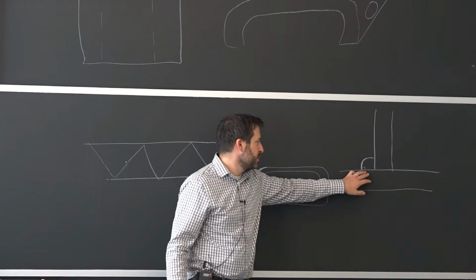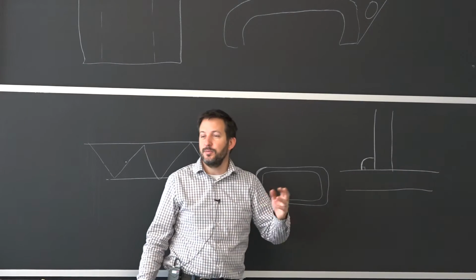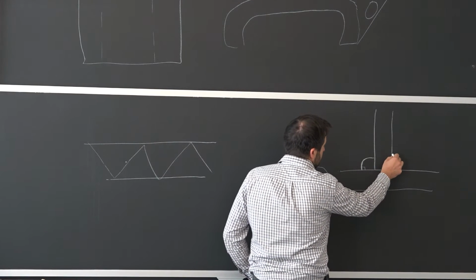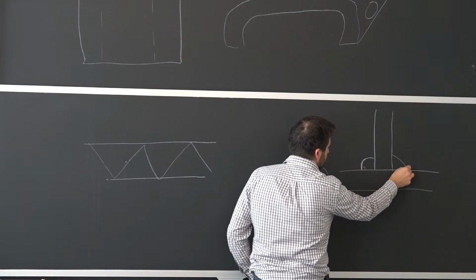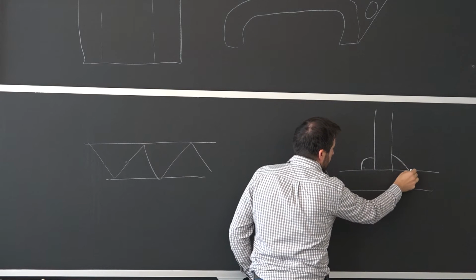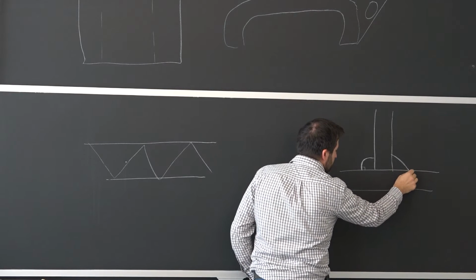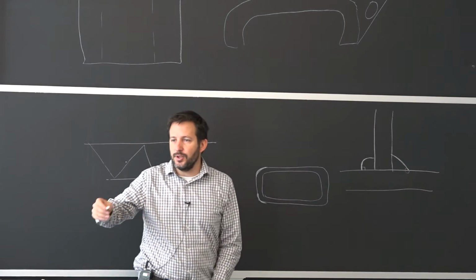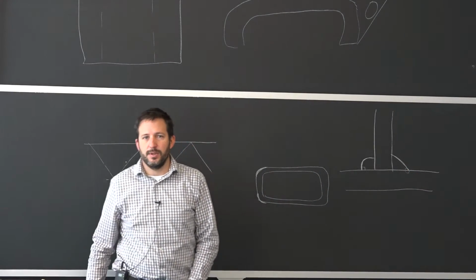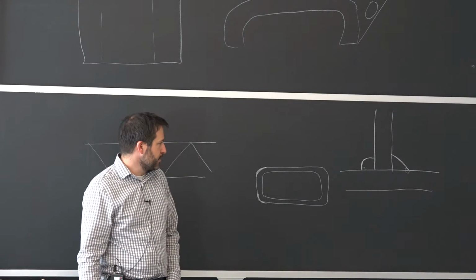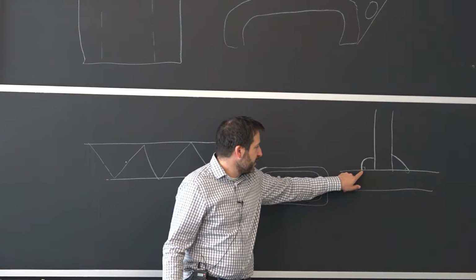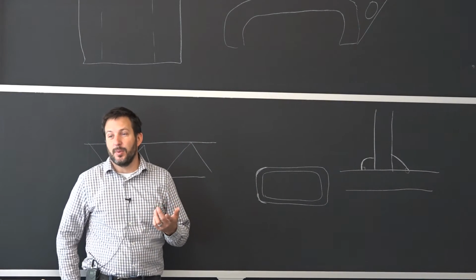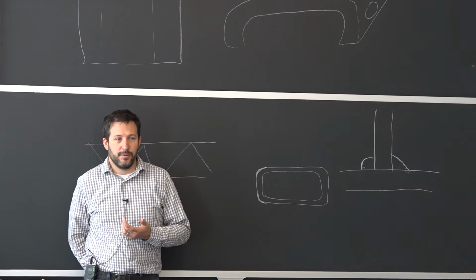When you heat up close to the melting point, this material, it's a liquid with a liquid, so it will spread, and let's say we'll do on the other side, we'll do a good one. The good one would look like this. So here you have a good contact angle, and it shows that both cases were fused, and now it was just a competition to extend an interface between the liquid and the fusion zone. So seeing that 90 degree on a weld is the first worry about not having enough fusion.